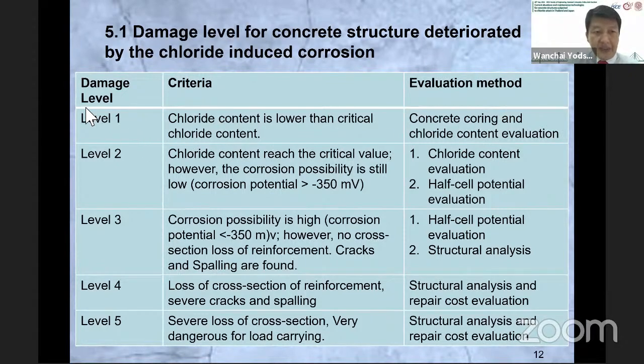For example, if your structure is in level 1, the criterion is that chloride content is lower than the critical chloride content. And for the evaluation method, we use concrete coring and chloride content evaluation. For example, at level 2 of damage, chloride content has reached the critical value. However, the corrosion possibility is still low and the half-cell potential is more than -350 millivolts. And for the evaluation method, we use chloride content evaluation and half-cell potential evaluation.